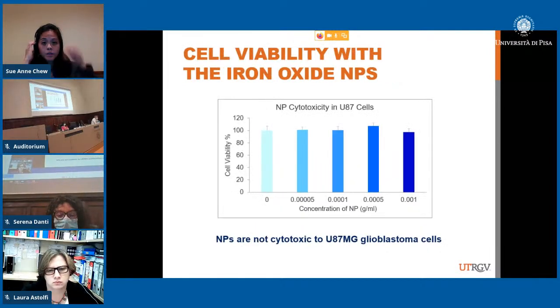And so the next thing we wanted to do is look at how this system will affect the glioblastoma cells. So U87MG cells are common glioblastoma cells, and it's the one we are also using in our lab. The first thing, although the literature has shown that this nanoparticle is not cytotoxic, we want to make sure that at the percentage that we were using in the scaffolds, it is not toxic to the cells. We don't want the iron oxide to be the one killing the cells. So we found that they were not toxic compared to the control.